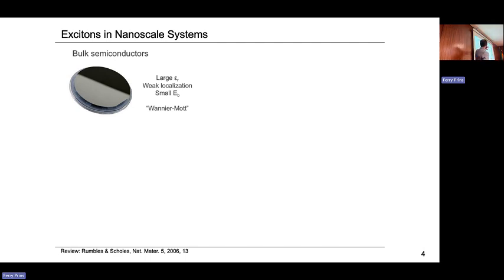Characteristics: well, you have a large epsilon, so dielectric constant. You have weak localization of your excited state, which means that your charges dissociate instantaneously, which results in a very small exciton binding energy. So the exciton that you create is basically just free charges. In physical chemistry terms, we would call this a Wannier-Mott exciton. Only at low temperatures will you see the exciton, but otherwise you have free charges.